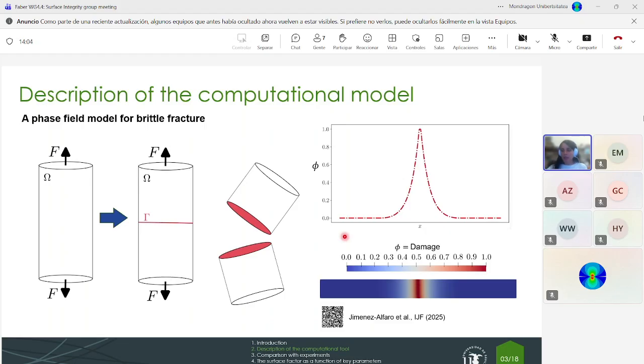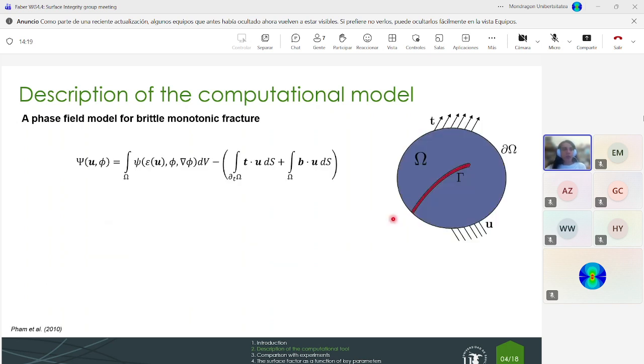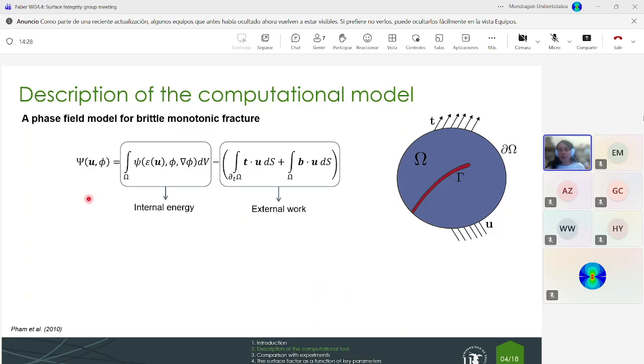When we have a phase field equal to 0, then the material point is not damaged. And when we have a phase field equal to 1, then the material point is completely damaged. So this is how we change a discontinuity by a smooth transition. We include this variable in the energetic functional of the solid that is defined as the sum of two terms. One is the internal energy and the other one the external work. This energetic function and the solution, the phase field variable and the displacement field, needs to fulfill three conditions.